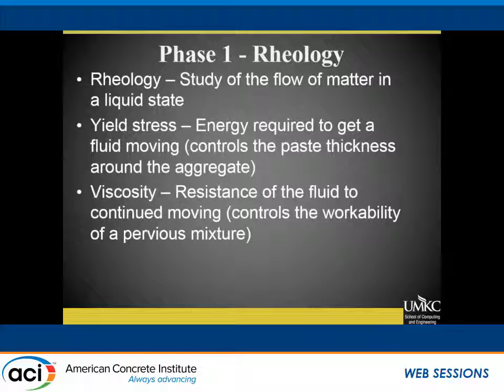So out of this, we get really two properties. We get the yield stress and the viscosity. Yield stress is how much energy it takes to get that fluid moving, and the viscosity is the resistance to keep it moving. And so the yield stress for pervious is going to control how much paste you can get around that aggregate piece. So a really high yield stress means I can hold a really thick amount of paste around that.